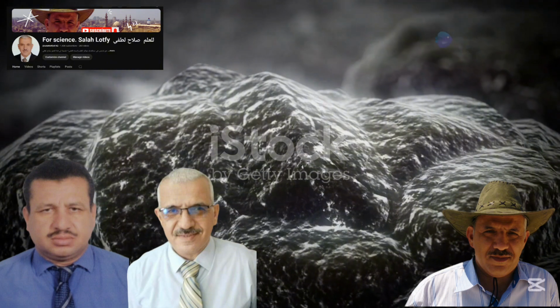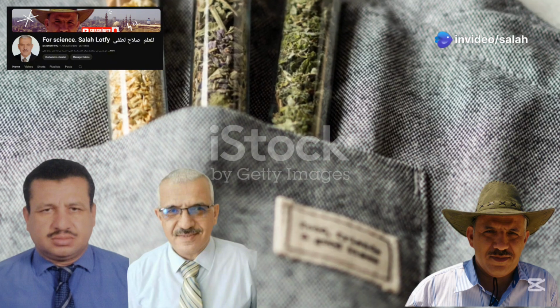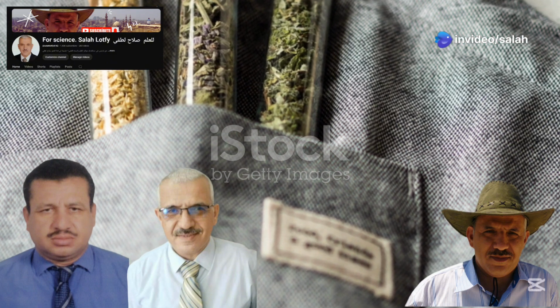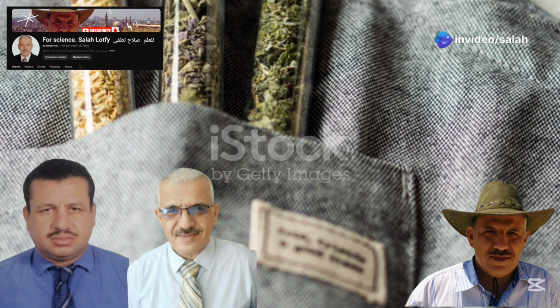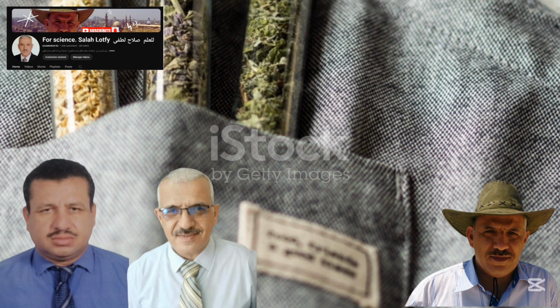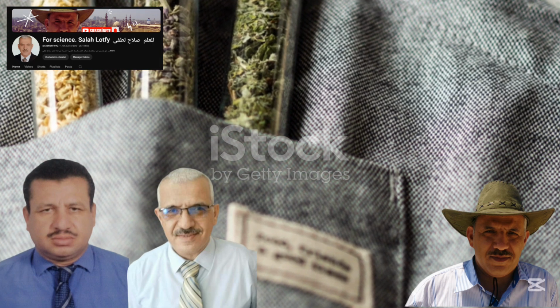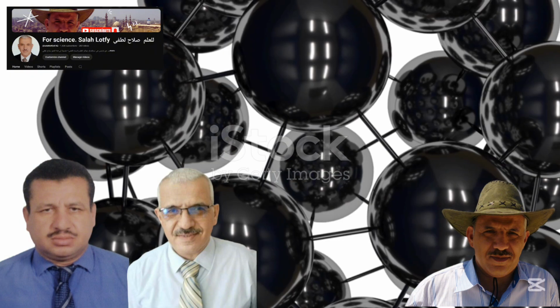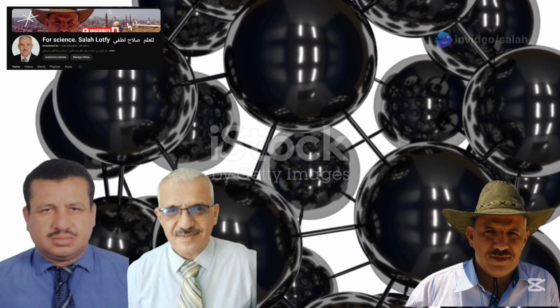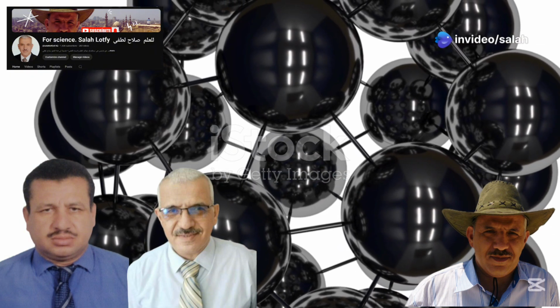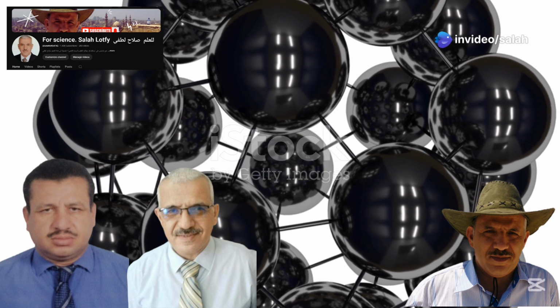High-magnification images revealed some cool details. Gamma-irradiated samples had well-distributed nanotubes embedded within the matrix, while ion beam irradiation caused surface disturbances, think microholes and crystalline structures. This means ion beams tweak surface roughness and porosity, potentially boosting mechanical strength and conductivity.